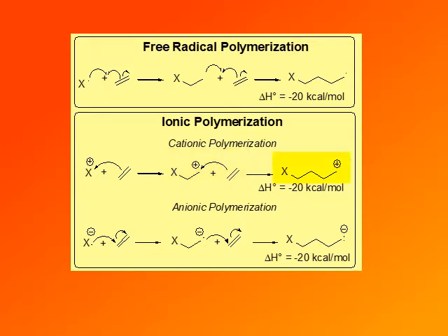What is interesting in this case is that once all of the reactants are used up, the reaction actually doesn't stop. We have to add some reagent, water or something else, to react with this intermediate carbocation to stop the reaction. So such polymers are called living polymers, because after reactants are used up, these chains are still so-called living. And we could add another different type of monomer and then generate another segment of the chain with a different type of monomer and so on. So this is much more useful, but also much more expensive way to carry out polymerization, living polymerization or ionic polymerization.